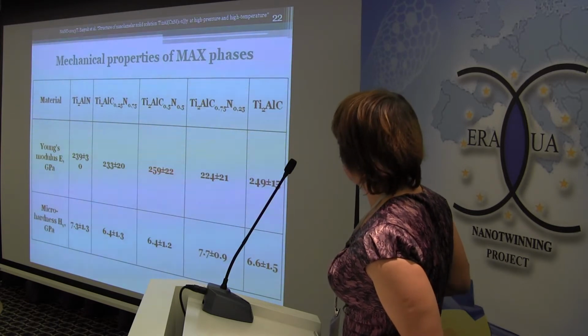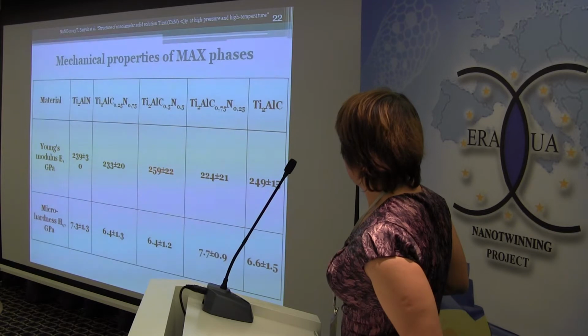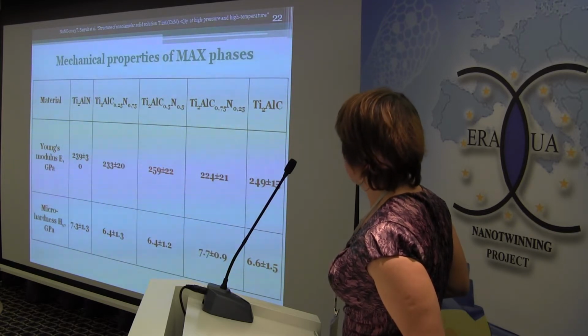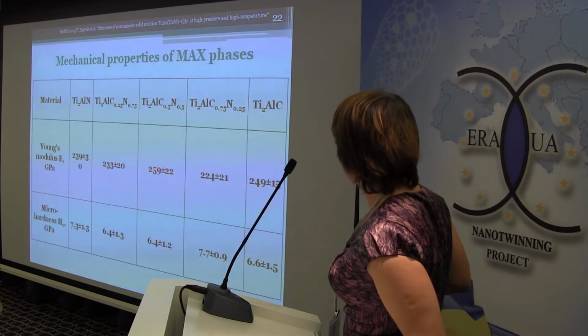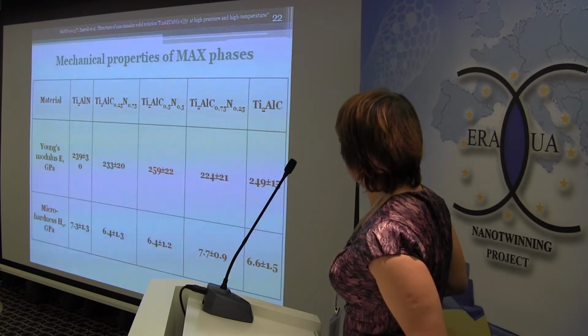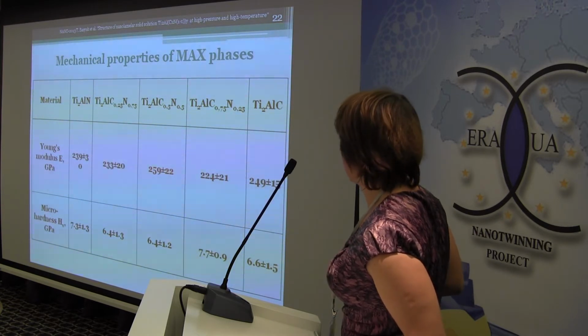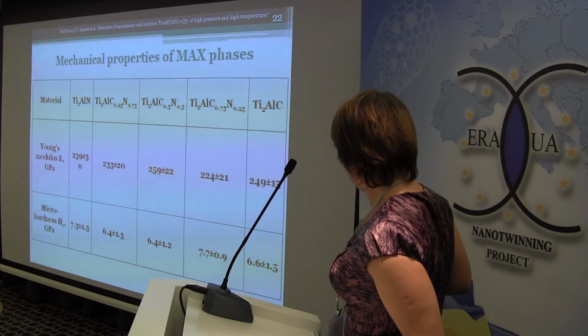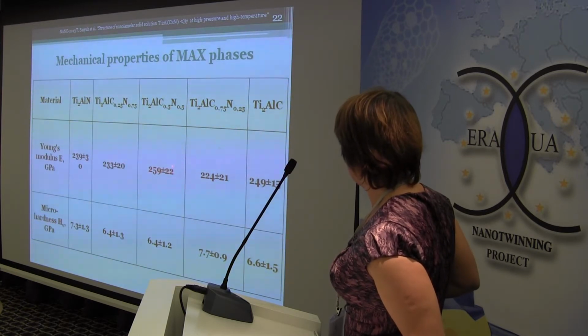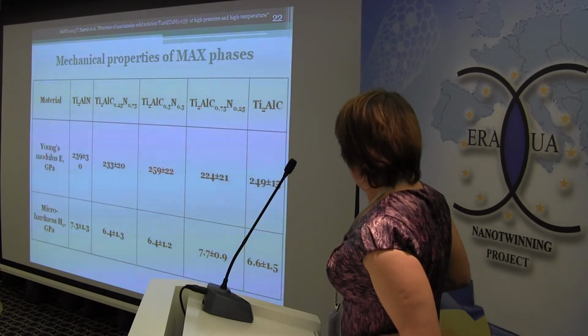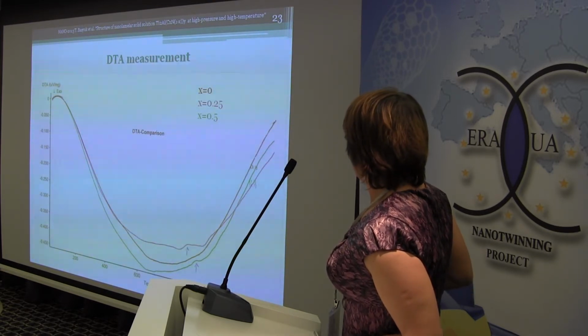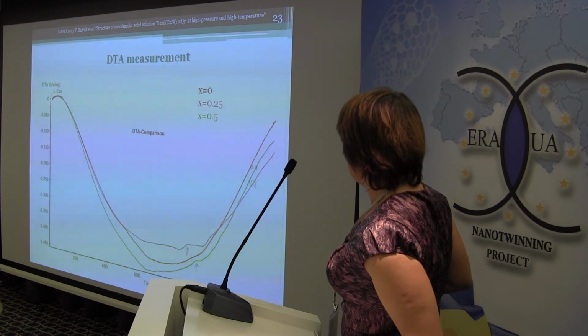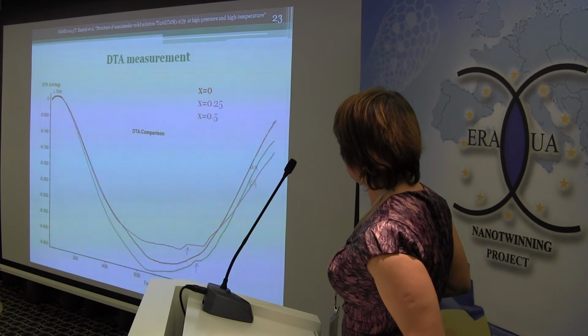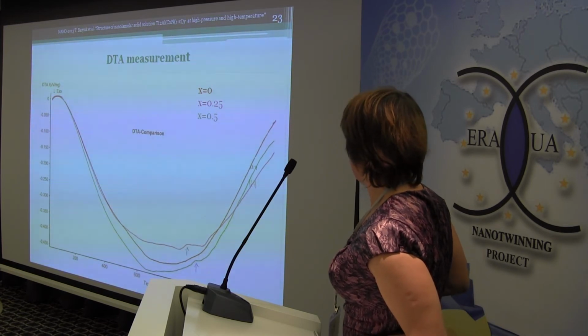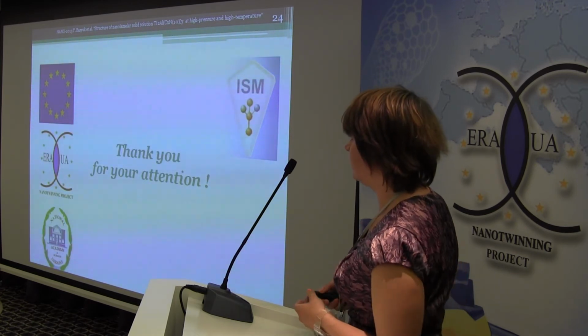For these densified samples, we measured mechanical properties such as Young's modulus and microhardness, and discovered that these values do not clearly depend on the carbon or nitrogen content, but for the sample with this composition, the Young's modulus was the biggest. And from DTA measurements, we estimated that oxidation resistance increases with increasing nitrogen content. So that's all. Thank you for your attention.